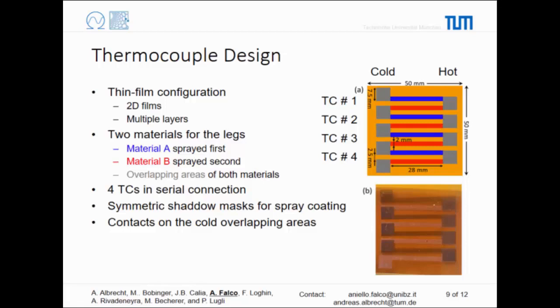We were triggered by an automotive company because they wanted to have a similar device, and Kapton was the perfect choice. But of course, we've got fully functioning thermocouples also on PET, so the normal plastic that you see on your bottles, because our processes are below 100 degrees. So they're all in ambient conditions and below 100 degrees.